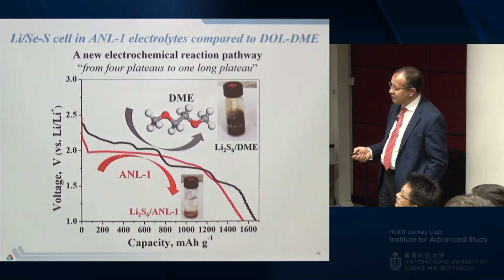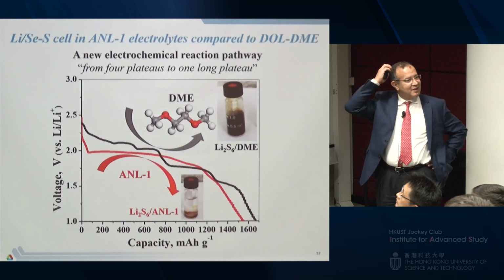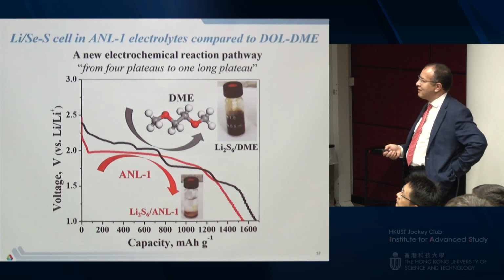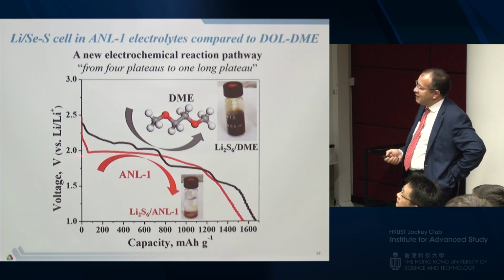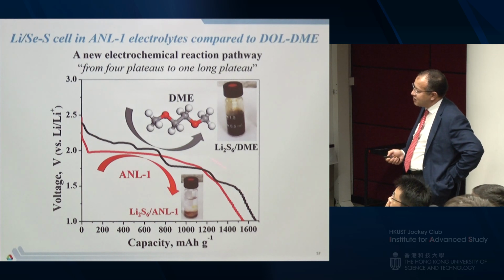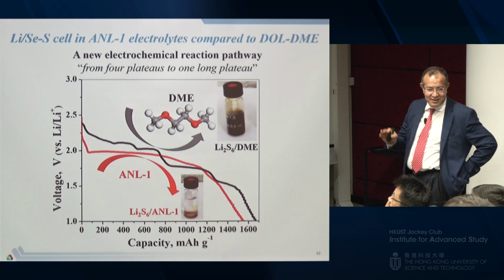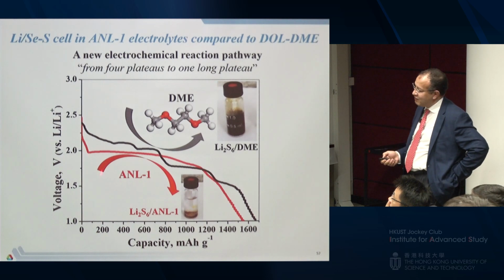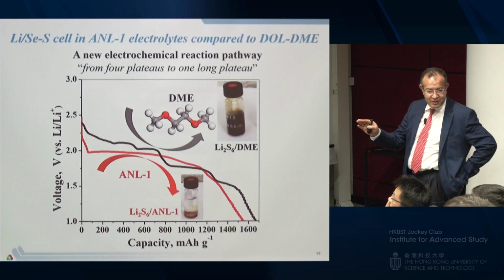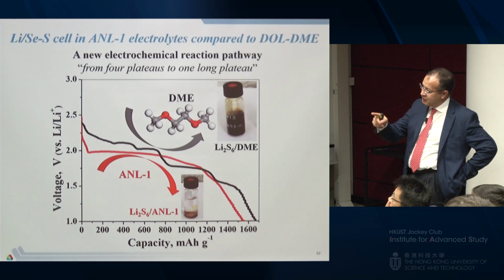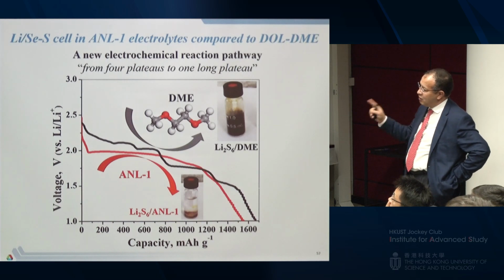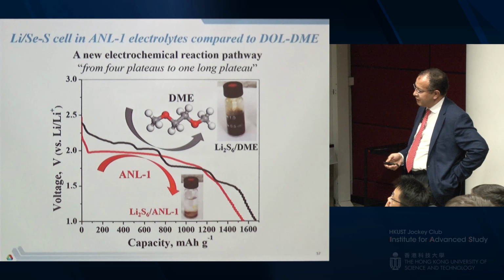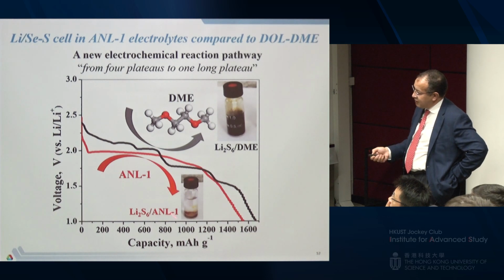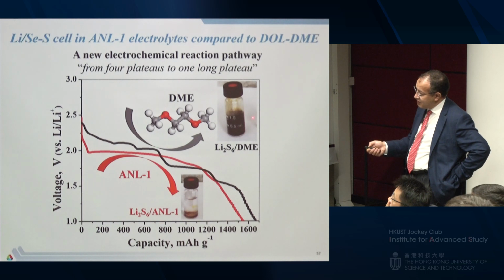Here is a new electrolyte. We call it ANL-1 because we are patenting it now. I promise I will share it with you later. If you use it, you can see clearly the pattern of the discharge is different to start with. That's great because it tells you that you have a one-phase reaction, basically moving from sulfur or selenium-sulfur to Li2 selenium-sulfur, if you want. And we did an experiment that shows that there is no dissolution versus the ether base.